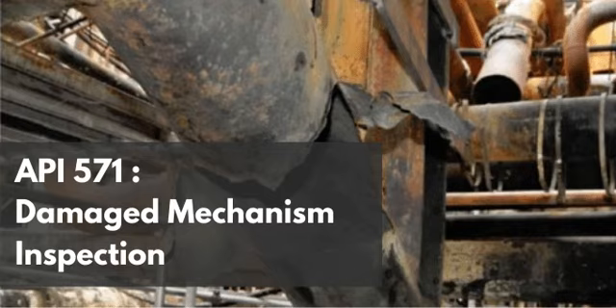But why not? Because, as we discussed with the metallographic detection paradox earlier, the damage is strictly microstructural. Ultrasonic testing looks for changes in acoustic impedance, like a void, a crack, or back wall metal loss. Radiography looks for density changes. But 885°F embrittlement doesn't manifest as metal loss. Exactly. There are no voids, no thinning, and no macroscopic cracks until the exact second it breaks. So standard in situ NDT scans looking for wall loss will literally print out a report saying the pipe is perfectly healthy. Yes. It will give you a profound, dangerous, false sense of security.